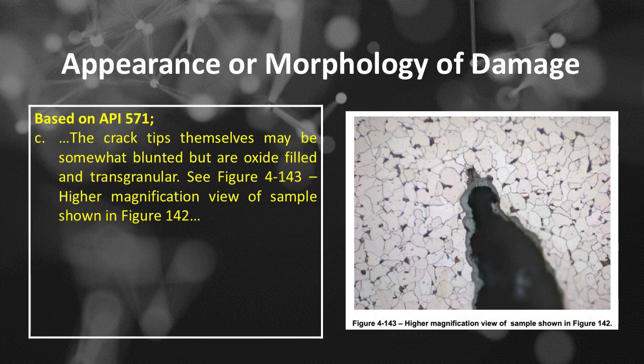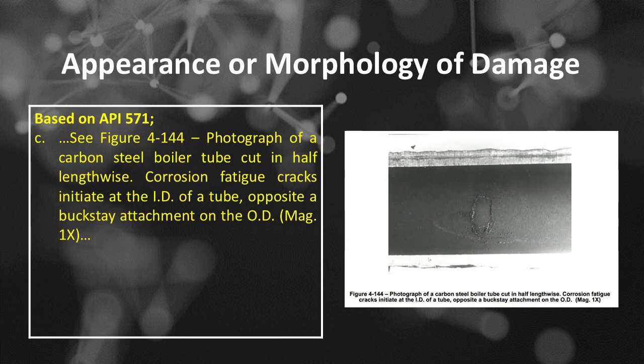The crack tips themselves may be somewhat blunted but are oxide-filled and transgranular. See Figure 4-143, higher magnification view of sample shown in Figure 4-142. See Figure 4-144, photograph of a carbon steel boiler tube cut in half lengthwise. Corrosion fatigue cracks initiate at the ID of a tube, opposite a buckstay attachment on the OD, magnification 1X.